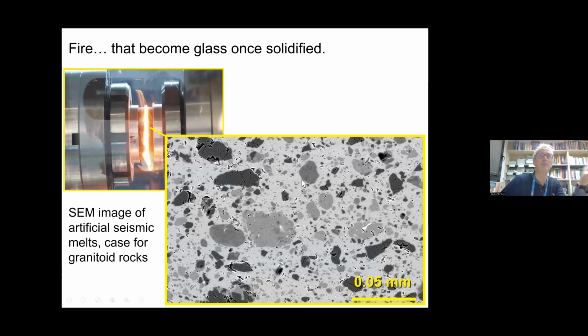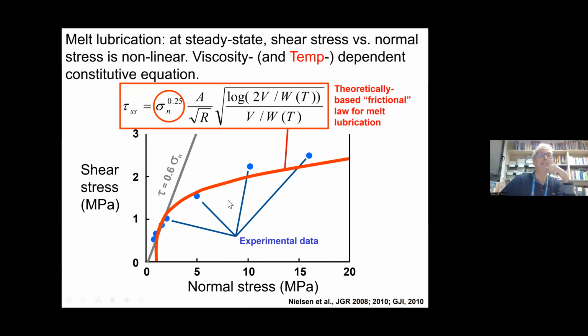Of course, there is melt, a lot of melt, a continuous layer of melt that is a glass once solidified, okay? And this is the kind of constitutive law that describes it. There is a nonlinear dependence of shear stress on normal stress. As you see, it goes with a power of 0 point something. Usually for gabbros, probably it's about 0.25. If you change the rock type, it may change slightly. But this is what you would expect, the gray line, for a typical friction coefficient of 0.6. And this is what you measure. And then you can fit it with this equation in experiments when there is a continuous layer of melt.